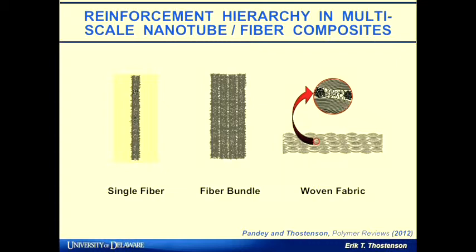When we hybridize these materials, we can think of this as a reinforcement hierarchy. With the carbon nanotube being very small, we can reinforce that small region around the fiber — what we would call the interphase region. The next step is transverse reinforcement in a fiber bundle, all the way up to the scale of the woven fabric. This approach of growing nanotubes on the fibers is something many groups are pursuing, and there are companies — in fact, one in the Baltimore area — commercializing this approach.